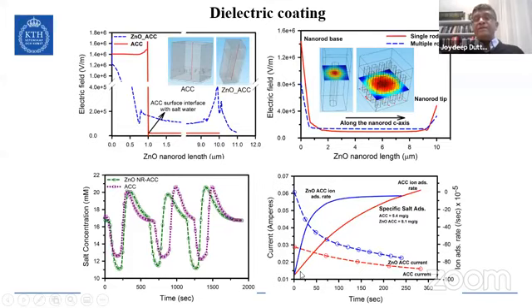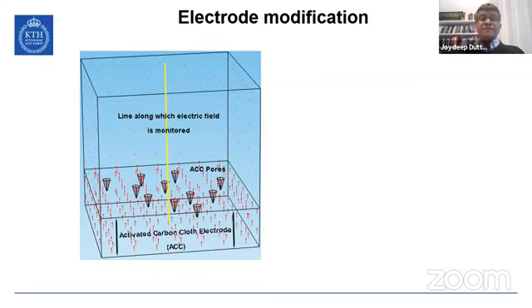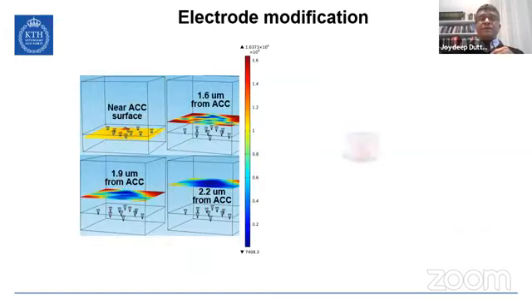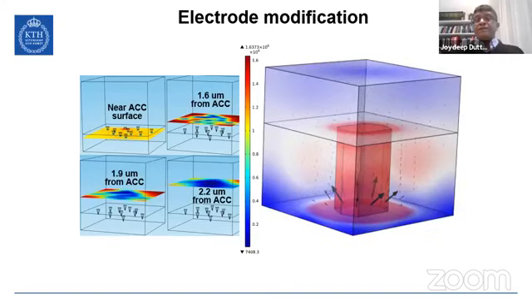putting dielectric coatings. This is the specific salt adsorption that we were getting, around 8 milligram per gram. This is an old result. These days, we are classically getting about 12 to 15 milligram per gram in the lab. The electrode modification, essentially, again basic physics, aligns the electric field from one electrode to the other. And by using a rod, we are able to have a very high electric field at the tip, and that helps in the ion adsorption as well.